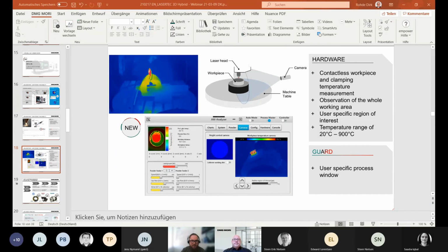And thin walls in a high structure, you have to go slowly, reduce the laser heat, have the heat impact very, very little. Completely stress relief, depending on material. Yes, typically some must be stress relieved depending on geometry, some not.